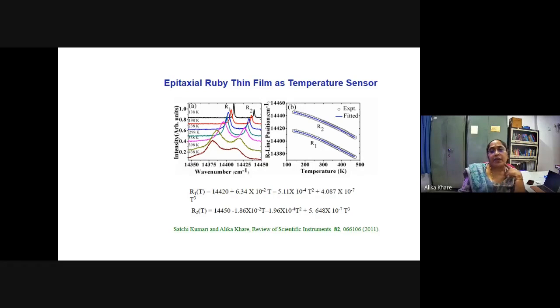One can see the variation from 100 Kelvin to 500 Kelvin - I have shown it up to that range, and one can see good variation. Earlier we used to think the sensor should be linear, but now with very good advanced data analysis techniques, we need not have the sensor be linear. We can use data analysis and a calibration curve, so even if the sensor is non-linear, it doesn't matter - these can be very well used.